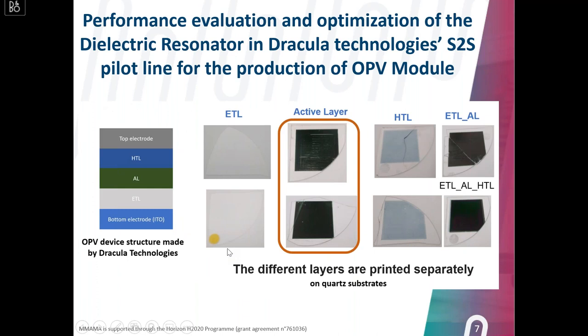Okay. So I will start to give you some results, maybe the most important results, based on these two different techniques. I will start with the evaluation of the performance of our devices and our printed layers based on the dielectric resonator technology. In our pilot line, here we see the device structure adopted by DRACULA Technologies, and we can clearly see that we have five layers. We can even obtain three layers, but in this particular device structure, we have four printed layers: the ETL, the electron transporting layer, the active layer, then the hole transporting layer, and then of course the top electrodes.